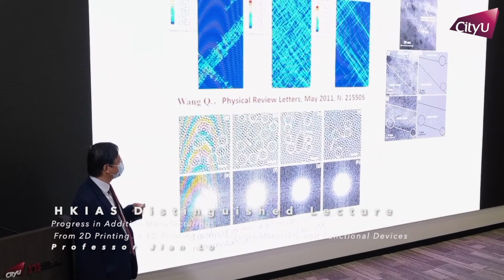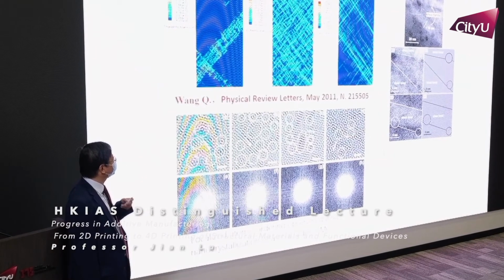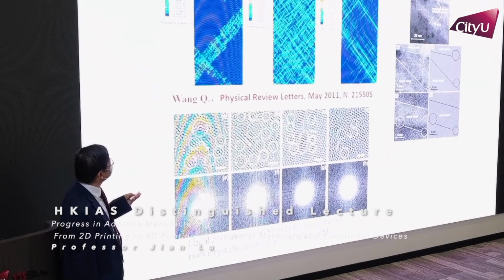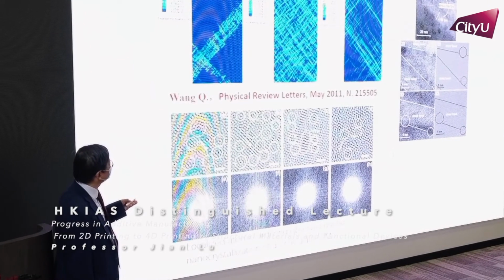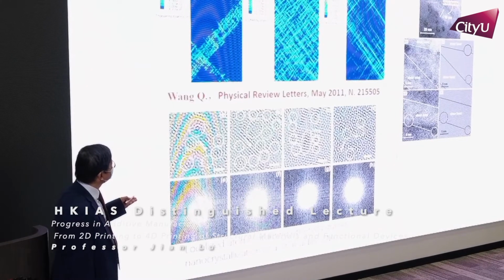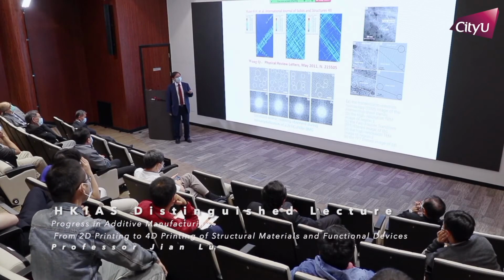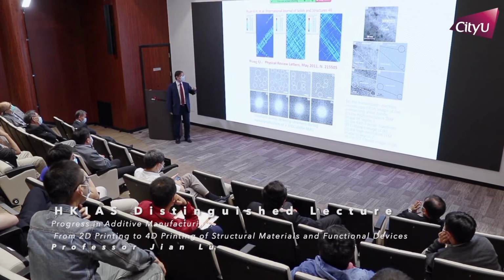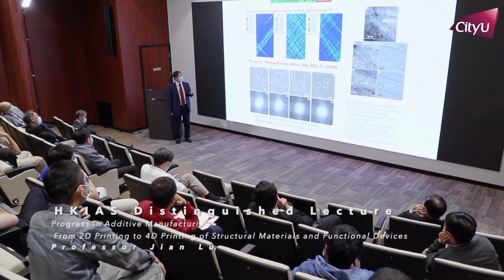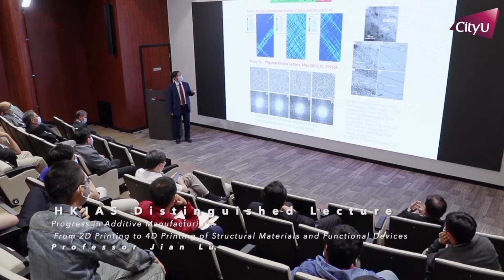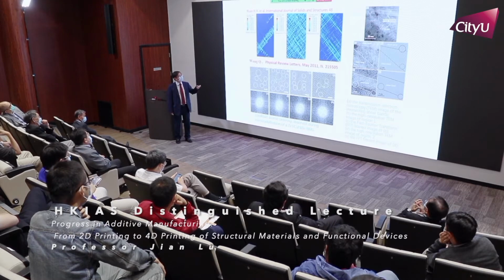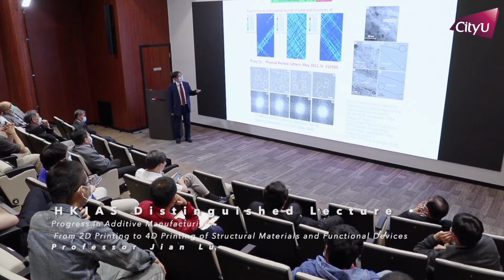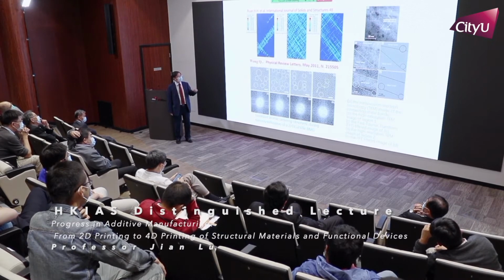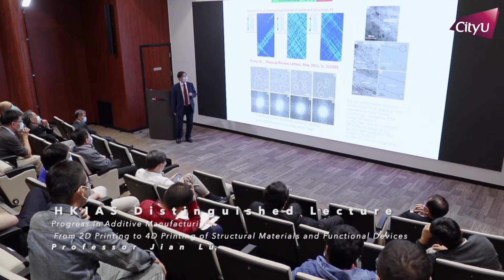So the example I show you is metallic glass combined with a very small nanocrystal. So why do we have this idea? So 10 years ago, basically by the simulation, we observed if we can mix two materials at atomic level, okay, with the same composition, say, with only 20% mechanical properties difference, we can generate a so-called multiple shear band failure mechanism. Because the metallic glass is like the normal glass. When you have initiation of failure, it's very difficult to stop.